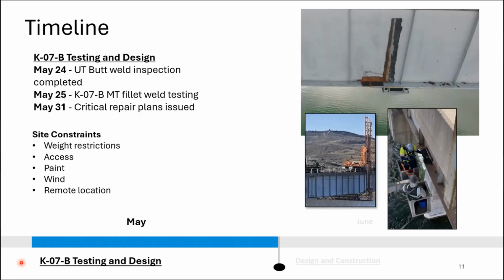As we started to get to the end of this month, paint removal at a couple of these butt weld locations revealed some individual fillet welds cracking between the flange and the web. And that kind of started some new investigation and changed some of our design ultimately. The critical bridge repair plans to fix only surface breaking cracks so that we could reopen to some limited traffic were completed roughly 1 week after the testing was complete and fabrication started and construction on those critical elements.